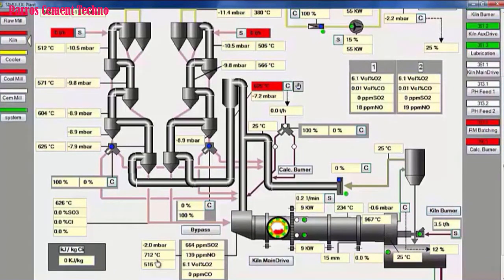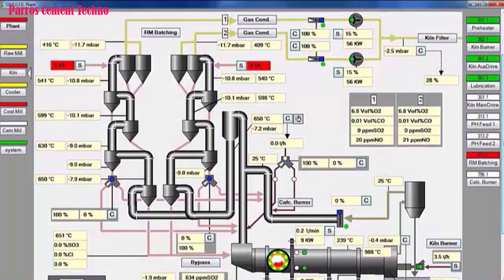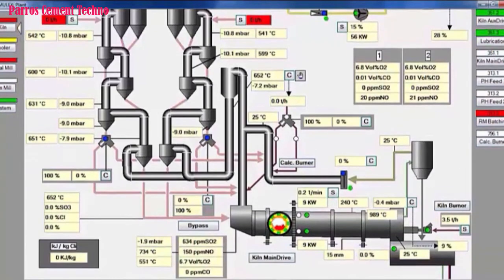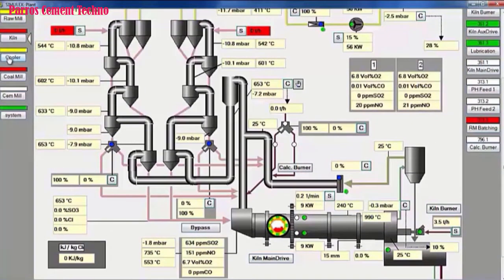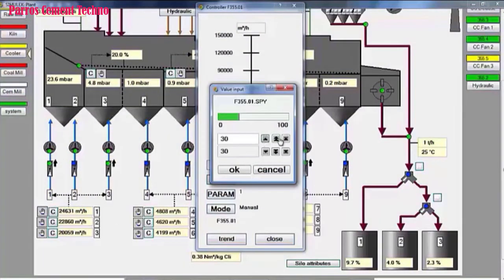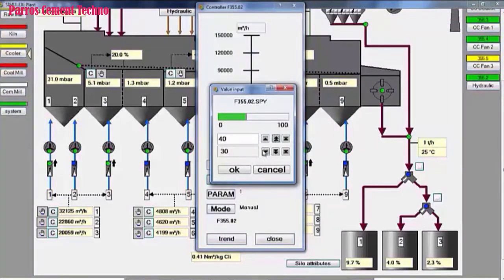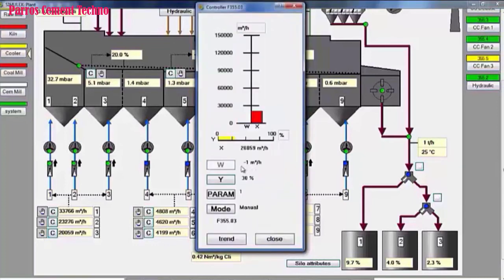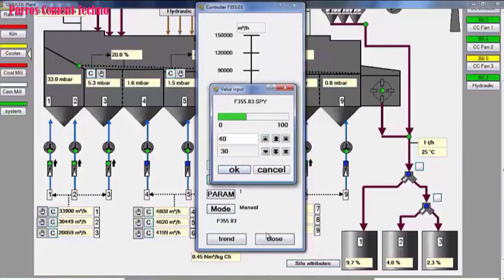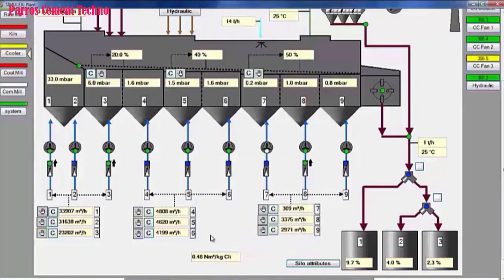the kiln main drive. The temperature rose a bit slowly, and the kiln shell temperature was already above 230 degrees Celsius. Currently, we have opened the preheater ID fan damper to 100%, and the ID fan speed is already 15%. Then this cooler ID fan damper opening is still low, then we have to increase the cooling fan damper opening from cooler. We increase the damper opening of the Grate 1 cooling fan from 30% to 40% each, in order to help the combustion air in the kiln, because we are already using coal as fuel.